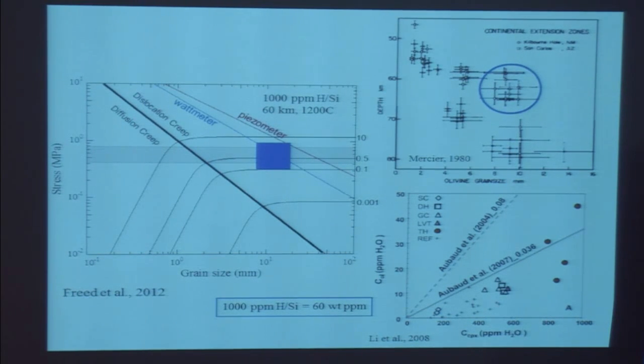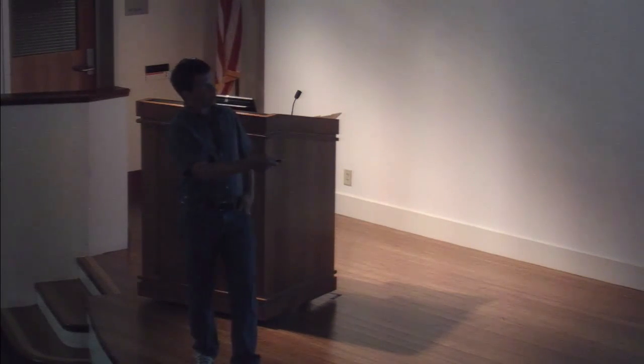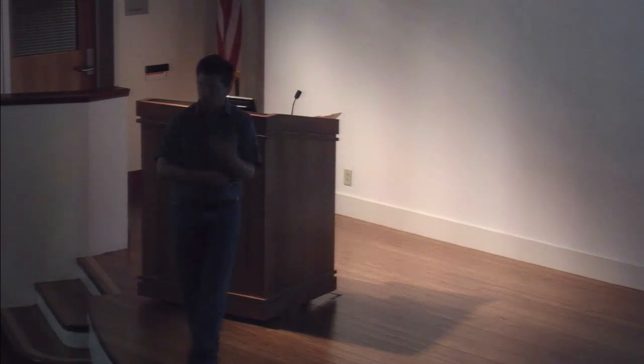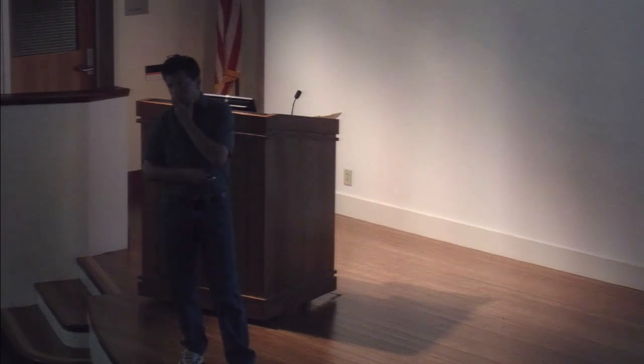This is not an exact test of the viscosity. It's a test of the viscosity, but using the constraints from the lab, it fits the data from what the grain size is, and it also fits the observation that you have a nonlinear creep response in that part of the mantle. So you get both the right magnitude of viscosity, the right magnitude of stress, the right grain size, and the right water content.